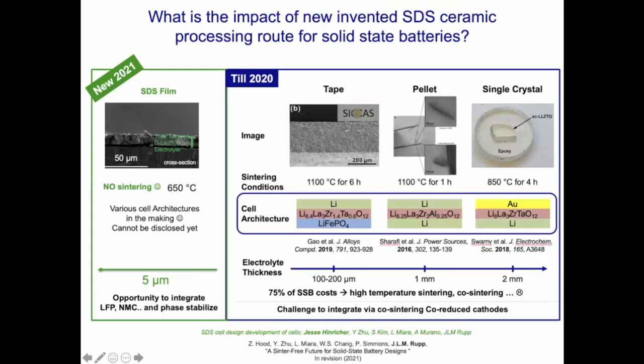So if you look in the full solid-state battery space, there's been tapes made, right? And these use very high temperatures. So we bring that down to 650, and you can see here a package of about 20 micron thickness, dense and crack-free, of such a lithium garnet electrolyte. And I think this is the door opener to go to other new cell designs in the future, not only for full solid state, but also for hybrid battery device architectures, where you could either think about having, for instance, also a liquid component in it and just using the ceramic separator to bring in lithium and possibly cobalt-reduced cathodes.